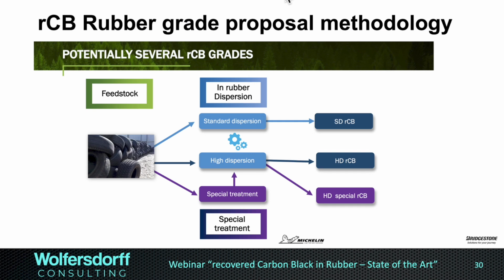And the overview and the idea was actually the tire companies copied the idea of having a standard dispersion and a high dispersion, which is the case for the precipitated silica for use in tires, where we have standard dispersion grade and the highly dispersible silica grades. Very often, silica dispersion is or has been in the past a problem, leading to the move in tire compounding from tangential internal mixers to intermeshing internal mixers, leading the way to additives. But the highly dispersible silica is now the norm, and the tire companies like to have something similar for the recovered carbon black. And for the recovered carbon black, it could be as simple as a milling grade below 10 micron for the highly dispersible, and maybe 20 or 30, a little bit less, for the standard dispersion recovered carbon black.